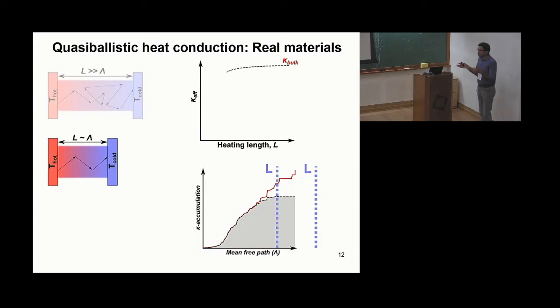Now, as you bring the hot and cold ends closer together, phonons with mean free path much longer than L are now transporting heat in a ballistic manner, which means their contribution is getting suppressed significantly. You see there is no accumulation happening in this region. For phonons with mean free path somewhat comparable to lambda, there is a suppression—the curve is still increasing, but at a smaller rate than Fourier's law's prediction. For phonons with mean free path much smaller than L, the contribution is untouched.